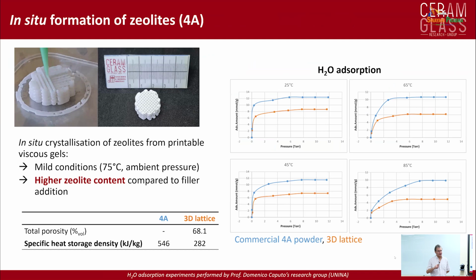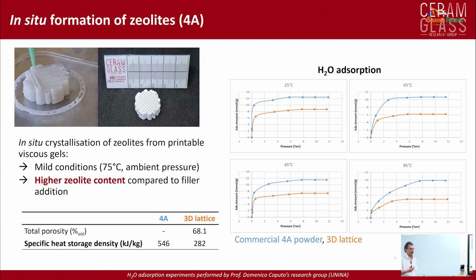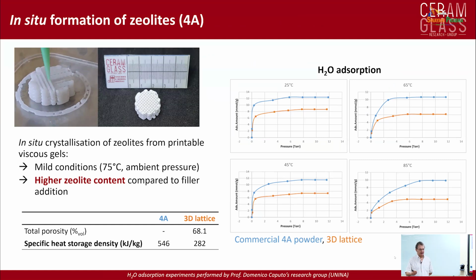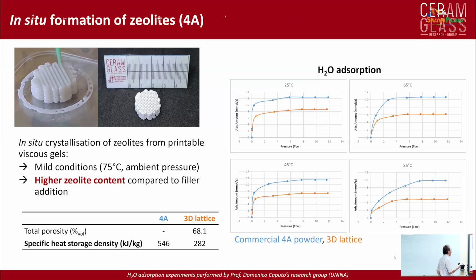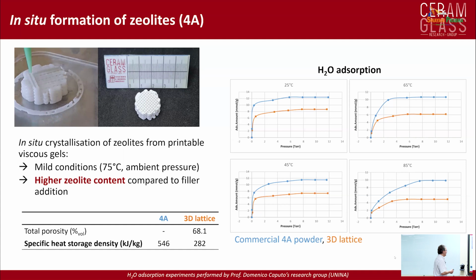I mentioned to you that geopolymers are considered cryptocrystalline materials, meaning that they have a composition similar to that of some zeolites, and the formation of zeolites can be triggered, typically by temperature and humidity. And we found one composition of geopolymers that allows us to obtain phase pure crystalline zeolite, and we have a patent on this. We used it, in this case, for water adsorption, with the idea of using the specific heat storage density for some applications.